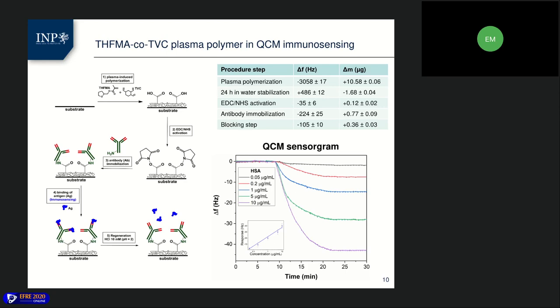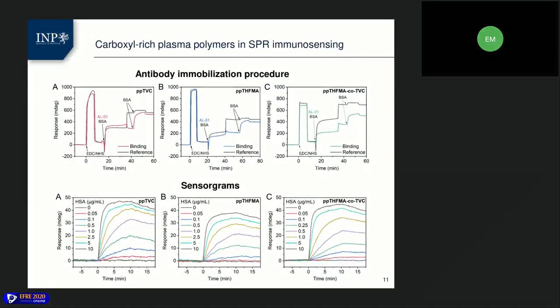The sharp drop in the frequency values is caused by the addition of antigen mass to the surface. Our plasma polymer surfaces offered a great performance of the biosensors. We had a stable baseline, good regenerability, selective and high response. Different concentrations of antigen were tested and the calibration curve showed the linear behavior of the sensor response. After successful QCM tests,